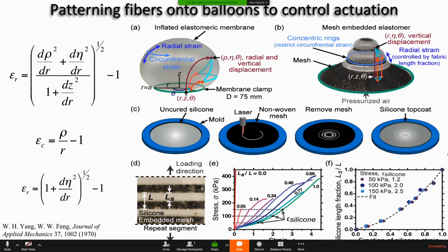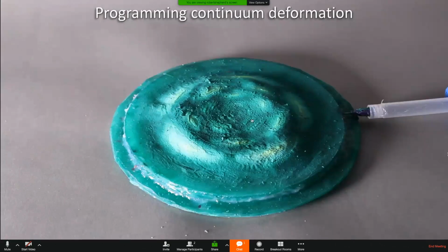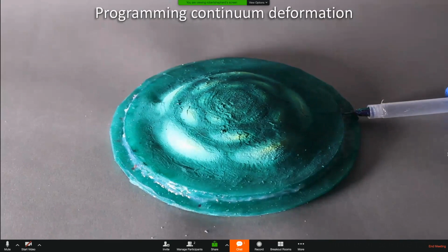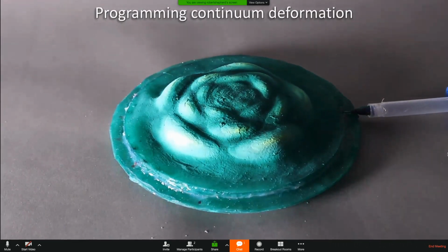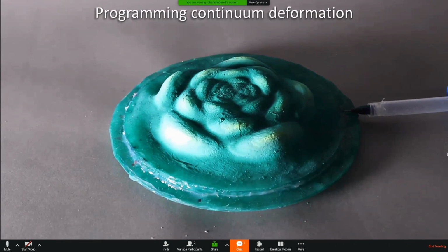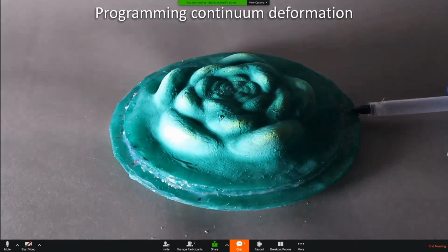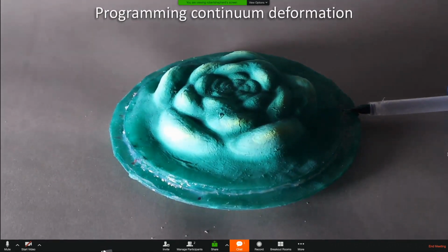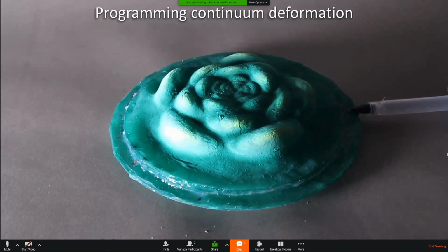And so then you can beforehand 3D scan an object, translate it into these projections of rings, pattern it onto this rubber surface, and then inflate it into positive, negative, and zero Gaussian curvatures, which in theory you can then use to produce any shape you want to. So now we can use balloons to make any shape we want to. We chose a low aspect ratio leafed aloe plant. And so these are ellipses we patterned onto the elastomer sheet, which we modeled as overlapping rings.